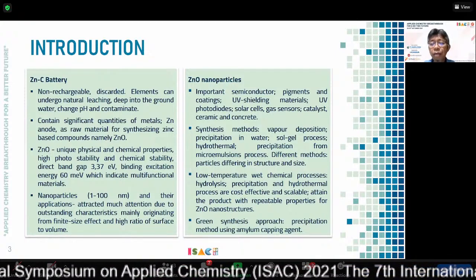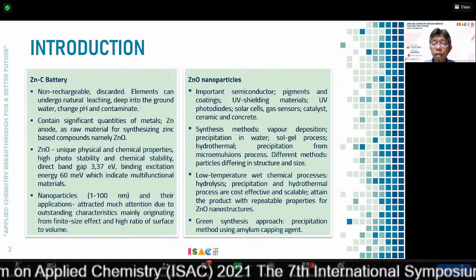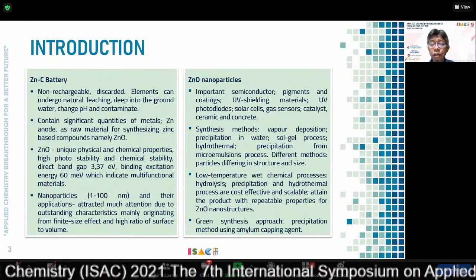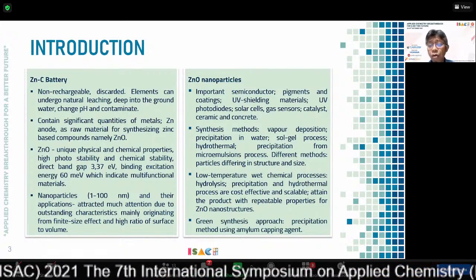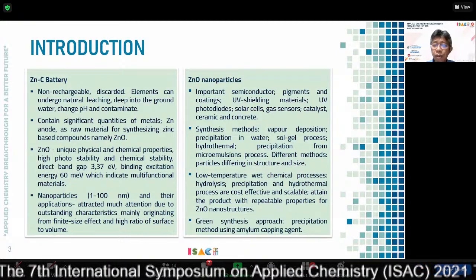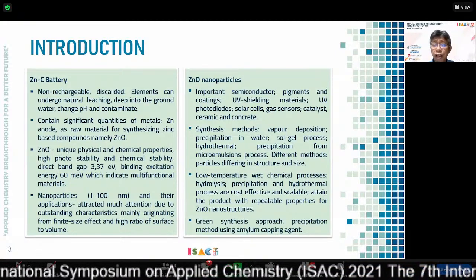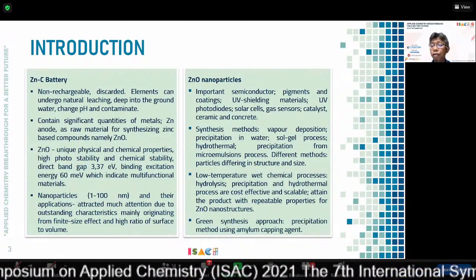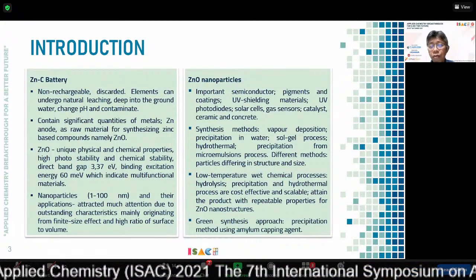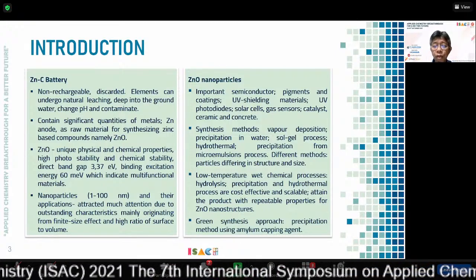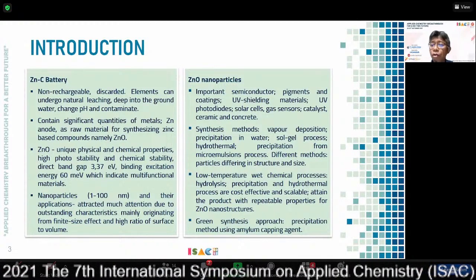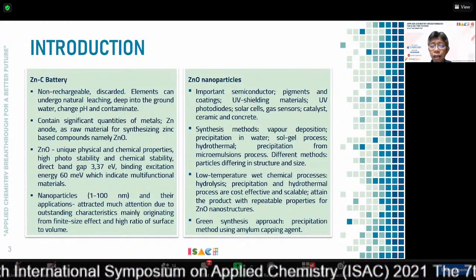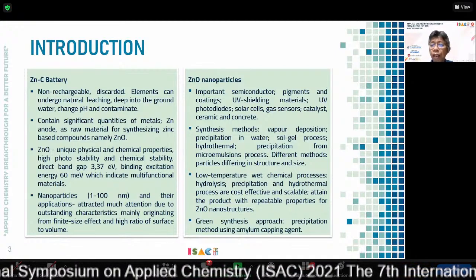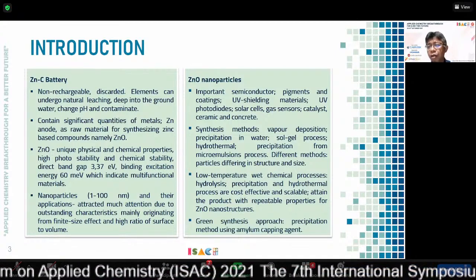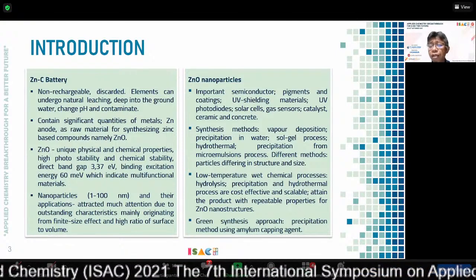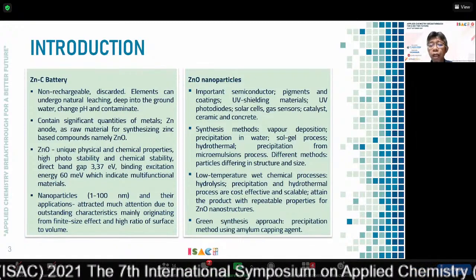And low temperature chemical processes are also interesting, such as hydrolysis, precipitation, and hydrothermal, because they are cost-effective and scalable. Particularly for precipitation, for instance, it can obtain a product with repeatable properties for zinc oxide nanostructures. Therefore, in our study, we use this kind of approach in order to obtain zinc oxide microparticles. And also we put in capping agents to control the growth of particle size in order to obtain zinc oxide nanoparticles.